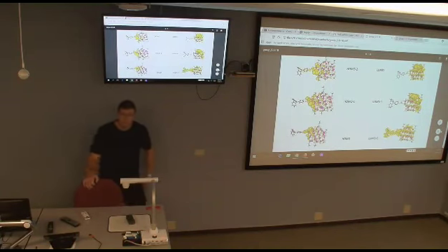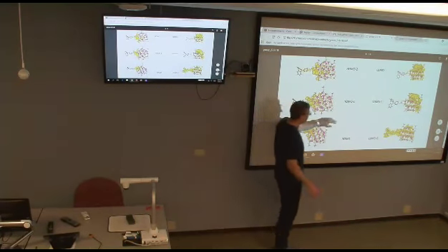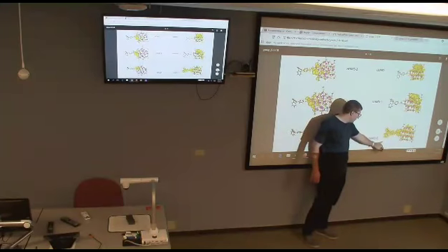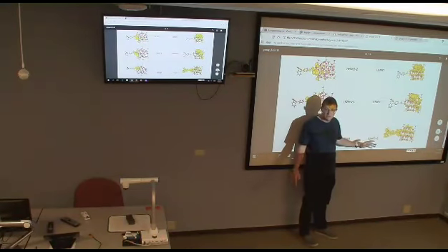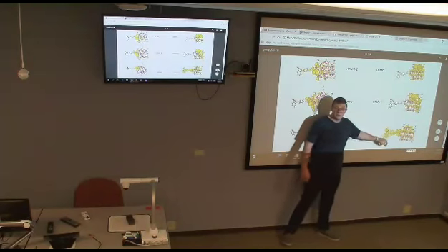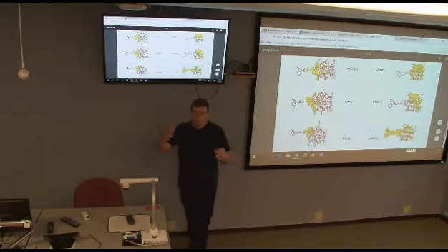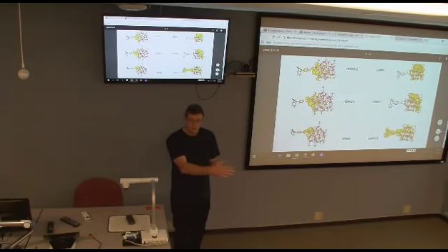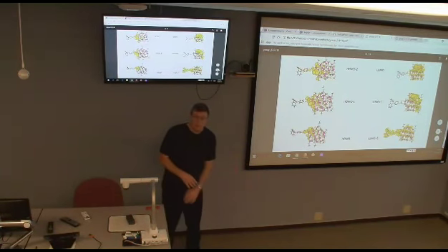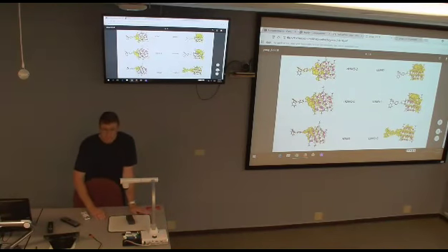Yeah, and with this system, there are a couple of states close to the valence band edge with a large portion delocalized on the organic dyes. Those states pop up with a transition to the dyes on, I wouldn't say a frequent basis. The top few go to the LUMO or LUMO+1, then you might have a couple sprinkled in that go to a state like that. So at the low energy range, you probably expect that you excite the quantum dot, not the dye. So you can tune excitation just of the quantum dot if you go to this low energy, despite these charge transfer states, which are probably not very optically active.